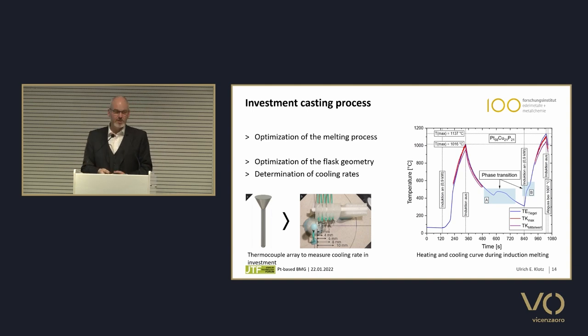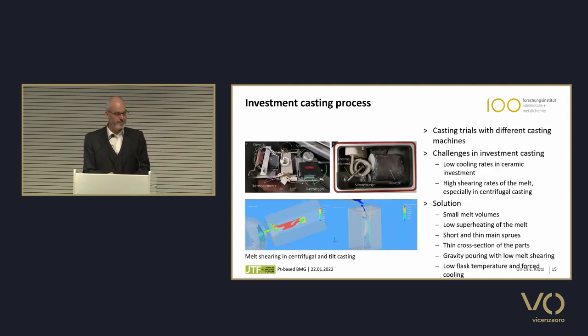This is the conventional heating-cooling cycle, and this demonstrates that the alloy has reached the right composition, because the temperature is in the right range for casting. Then after the second heating, we switch the induction off, and then we cast, in this case, at around 1,000 degrees. We did two casting trials. I already told you about the centrifugal casting, and we also did tilt casting trials.